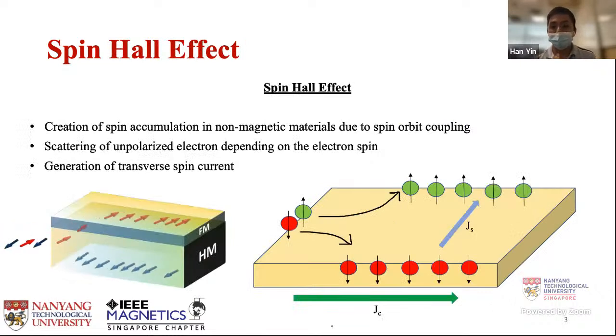So, spin Hall effect is basically a creation of spin accumulation in non-magnetic material due to SOC, spin orbit coupling. It's a scattering effect where if we send a charge current into a heavy metal, due to SOC, the electrons will be scattered differently depending on electron spins. So on the bottom left is an animation of the spin Hall effect, where we can see that the spins pointing into the screen are accumulated on top of the heavy metal, whereas the spins pointing out of the screen are accumulated at the bottom of the heavy metal.